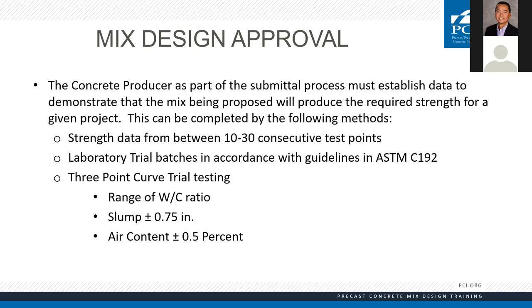The third way is a three-point curve — trial testing. In a three-point curve, we have three batches of concrete. We have to maintain a slump of plus or minus three-quarter inch and air plus or minus half percent. Then we also range the water-cement ratio: we have a target, one a little higher, and one a little lower. If all three points exceed our design strength, then we can submit that mix for approval. Strength data from 30 consecutive tests is obviously the most reliable means of proving out a mix.